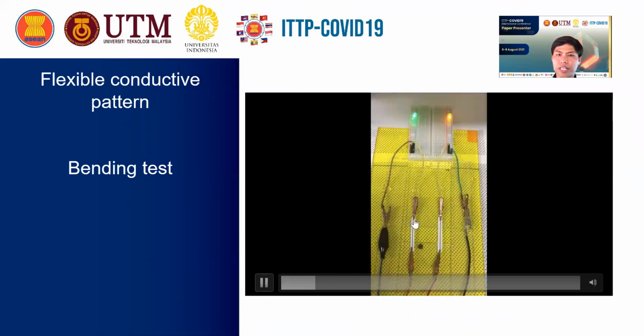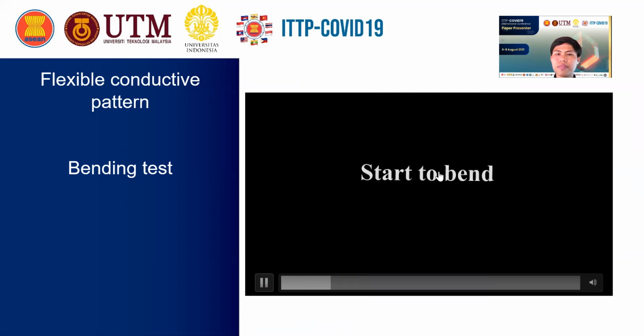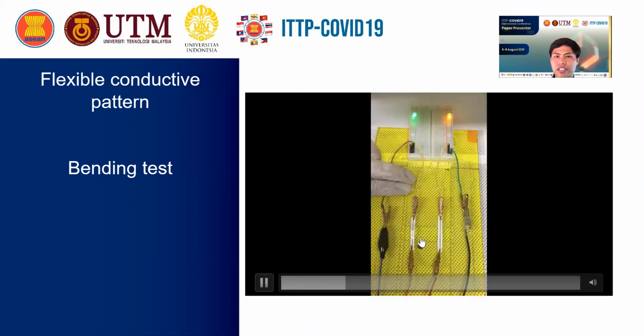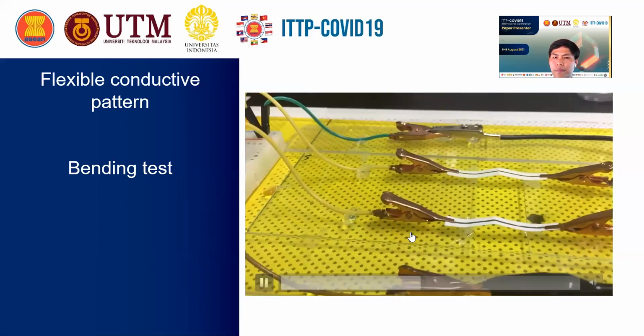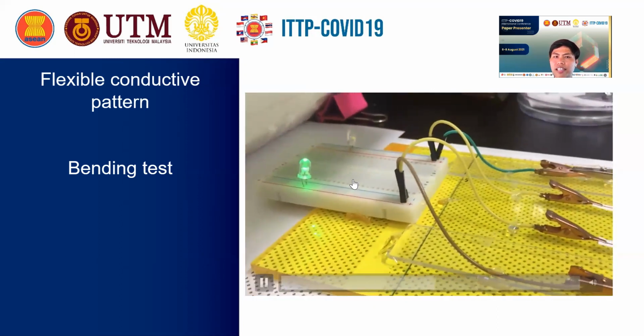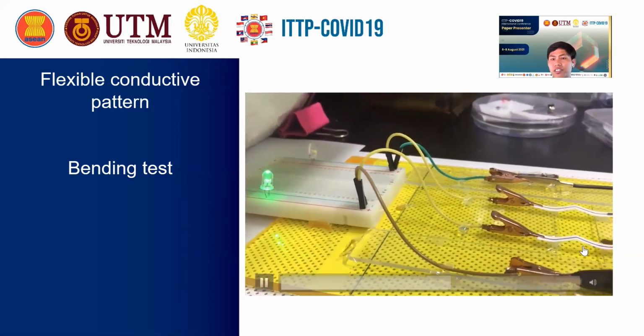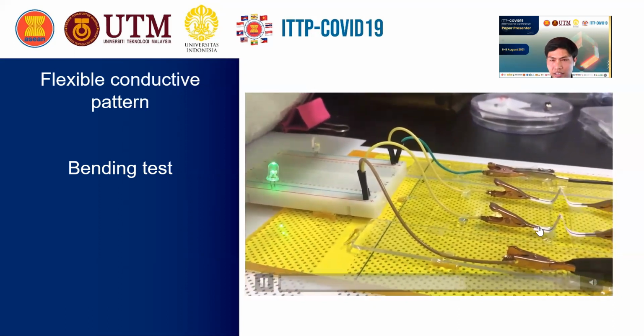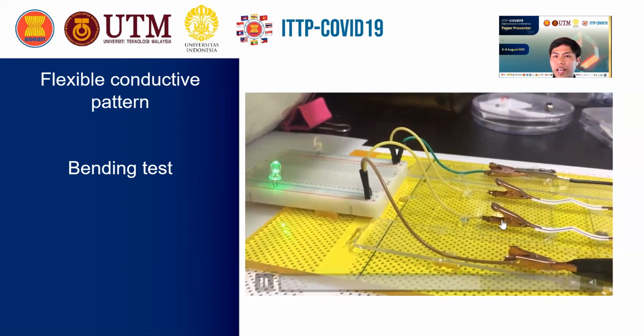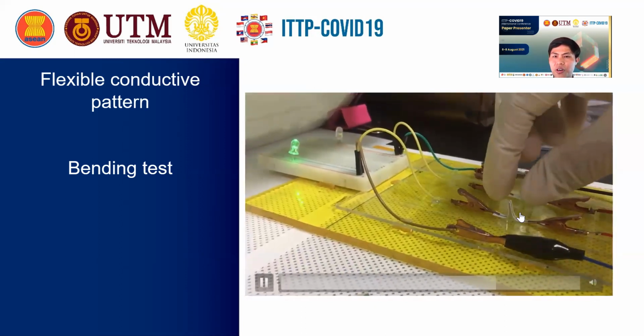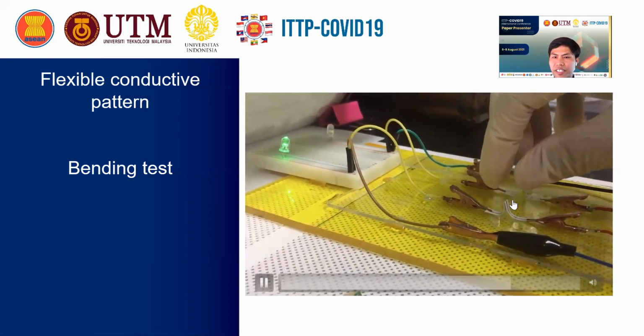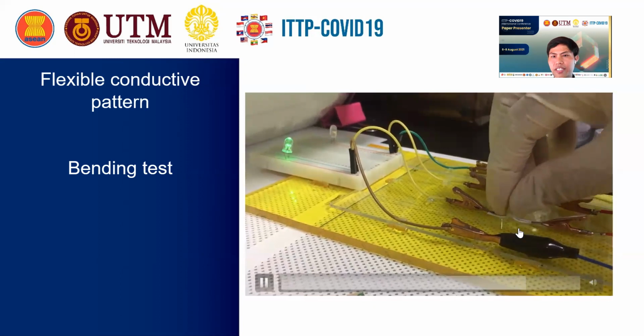When we print, the LED lights up at the beginning, but after just slightly bending, the pattern is broken. It is disconnected and cannot transport electricity anymore. But you can look at the PES substrate pattern: the silver nanoparticle pattern is still lining up. It means that this pattern is not broken. It still works perfectly even when we bend it a lot here. So, just a simple comparison: if you want to make a device and bend it, then our printing substrate can be a candidate for printed electronics.